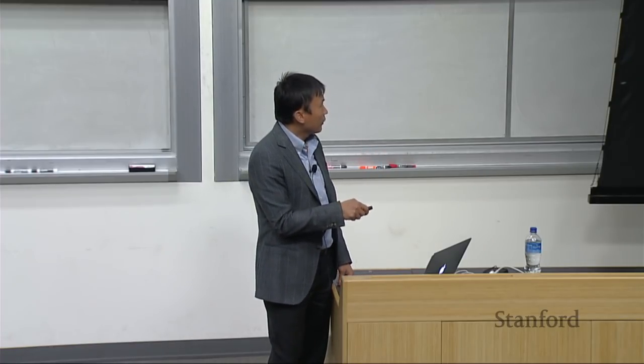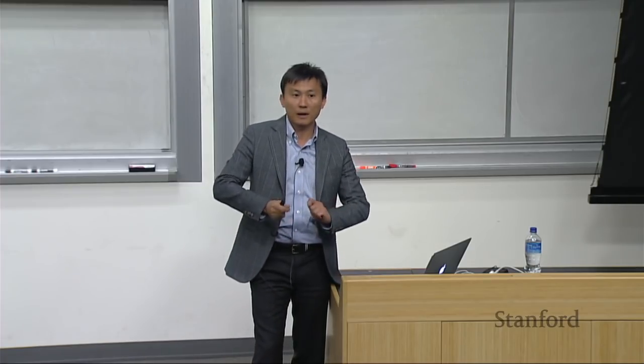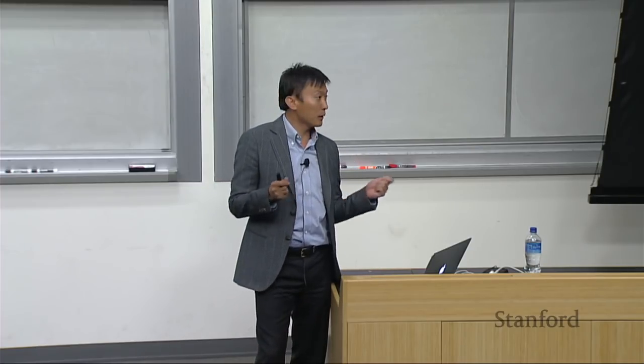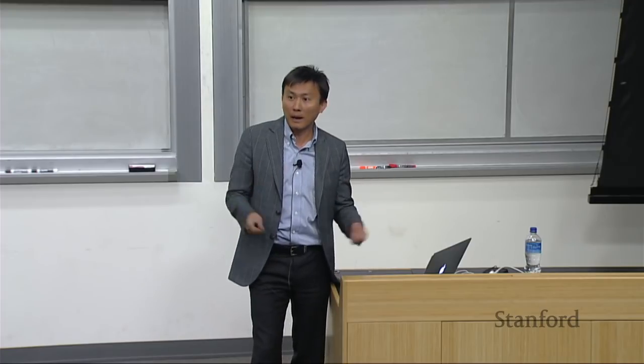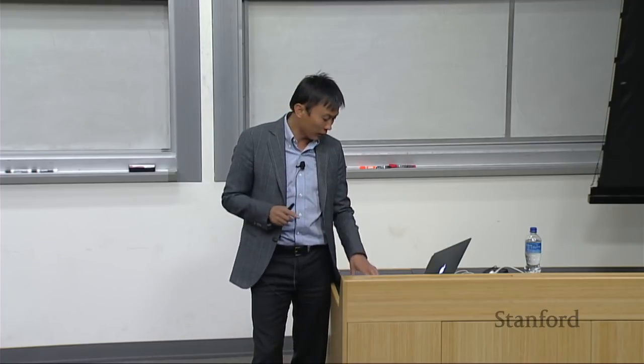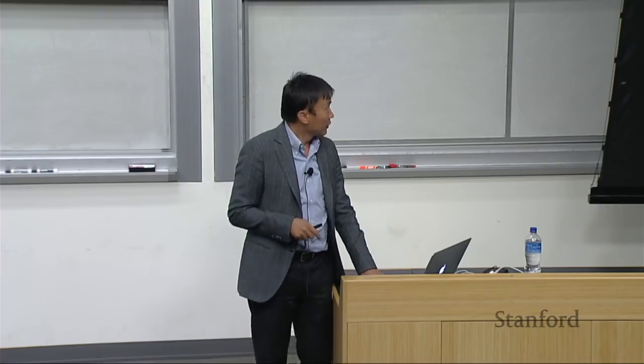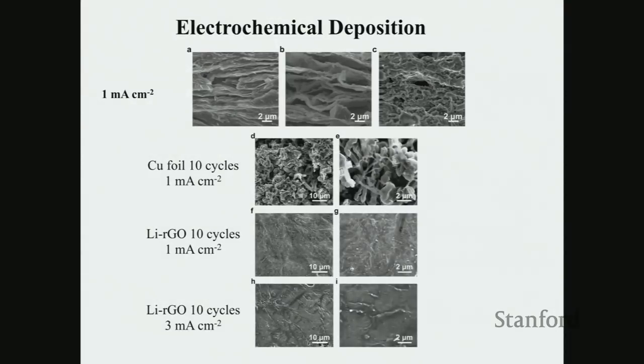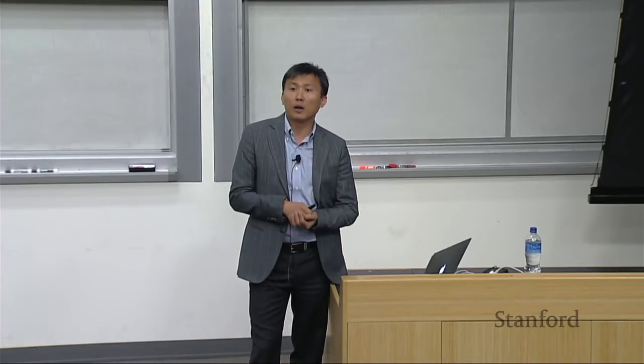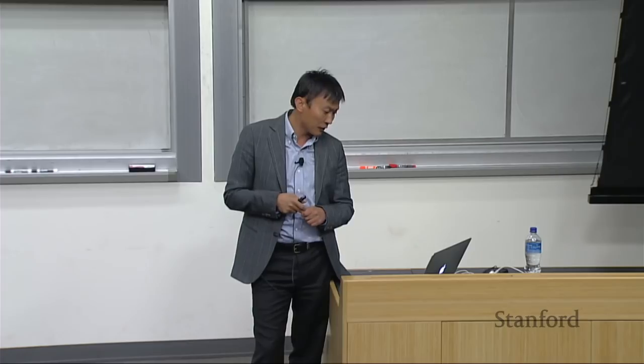Graphene oxide in this regard is the host structure for the lithium metal. And after this processing, this is flexible, just like a metallic foil. So this could be processed using the existing battery manufacturing machines. So now let's look at the deposition behavior. This is with reduced graphene oxide. After deposition, the surface looks smooth. If you deposit lithium onto copper foil, it forms dendrite. So we don't have those dendrite formations. This makes this lithium foil inside the graphene oxide a lot more stable, a lot safer.